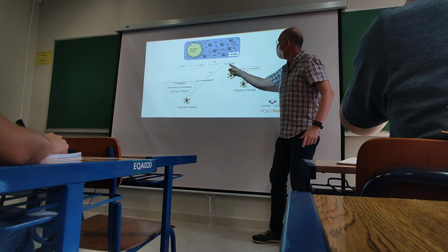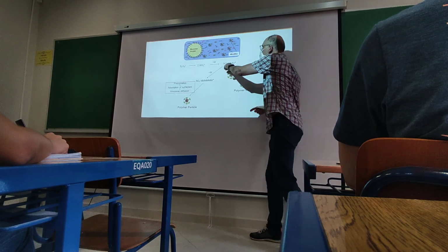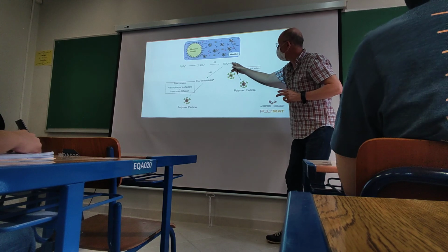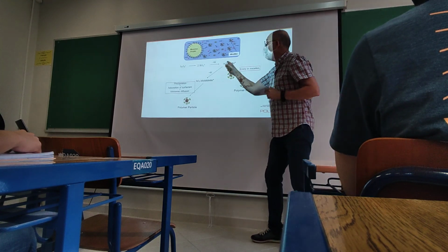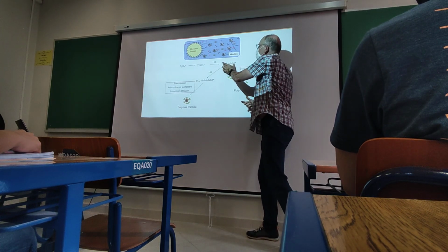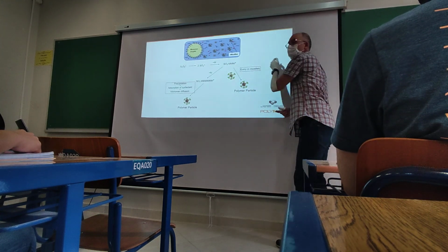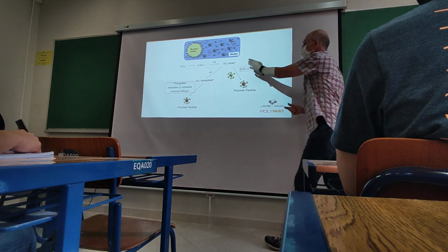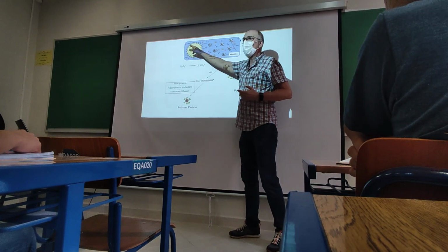So we will start forming what we call oligoradicals. So radicals which are more hydrophobic than the original initiator radical. So these radicals which are more hydrophobic by adding monomer, now they are more hydrophobic, and at a certain point they will be surface active. They become like surfactants. This is hydrophilic, and this is getting more hydrophobic. So this now can absorb onto micelles or droplets. Okay? So if they absorb, they are much more micelles than droplets.